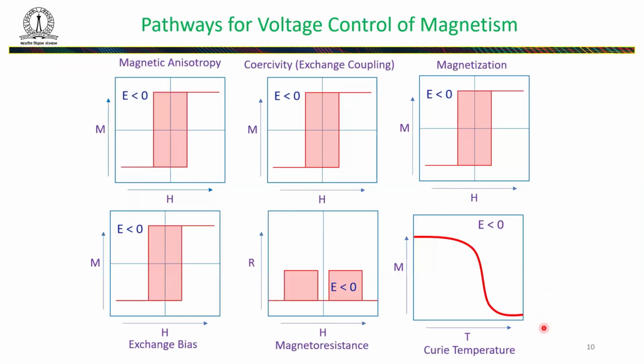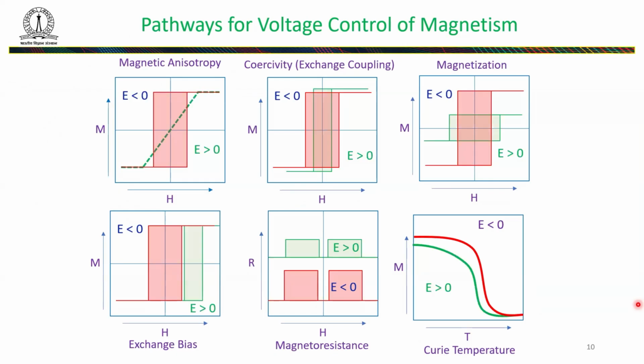Okay, so what we need to do is basically switch the magnetism with electric field. So you switch either the magnetic anisotropy, coercivity, magnetization, exchange bias, magnetoresistance, or Curie temperature. That means in one polarity of electric field, you have one of these magnetic states, and then you change the polarity, and you may get a different magnetic state. And if you somehow manage to incorporate that into a device and actually get two different resistance states, then you can use this for some sort of memory application. So this is what we have been trying for the last few years.